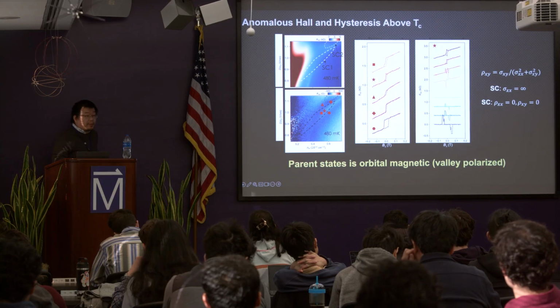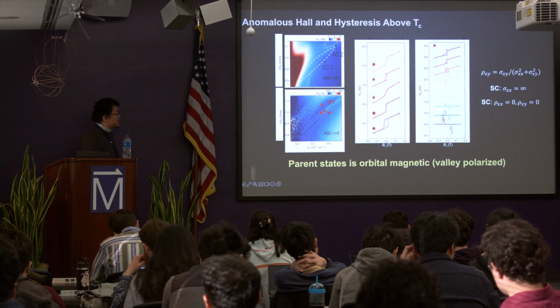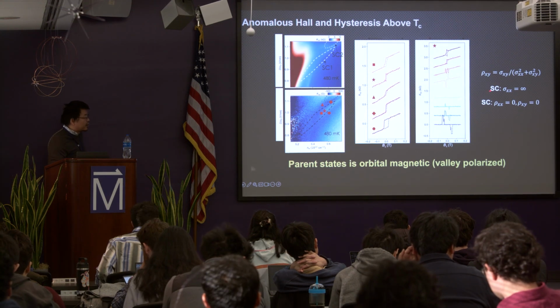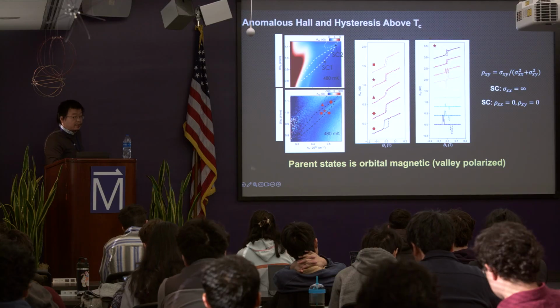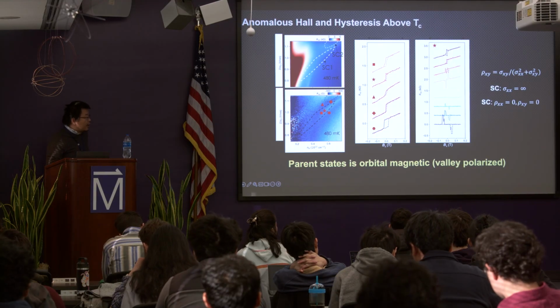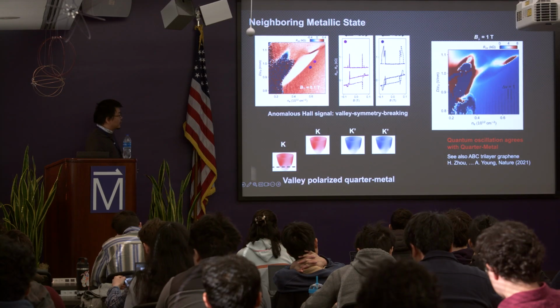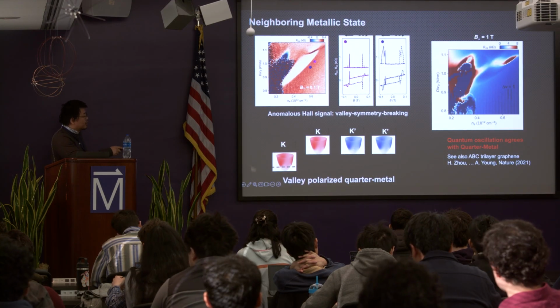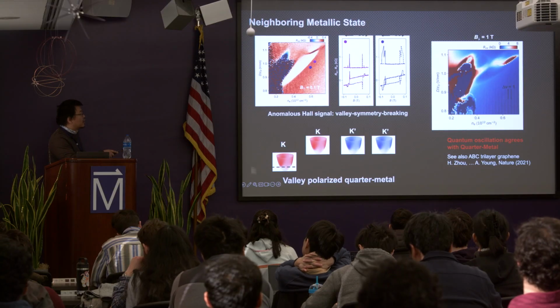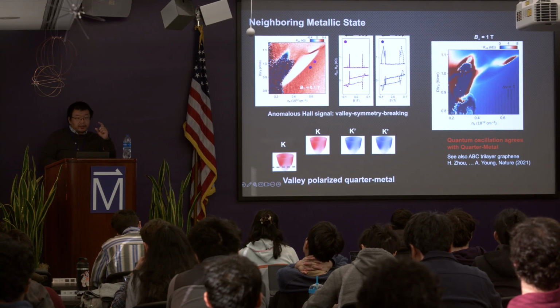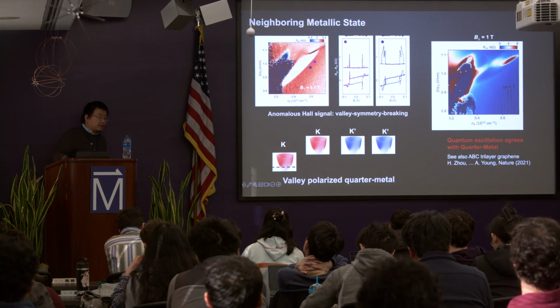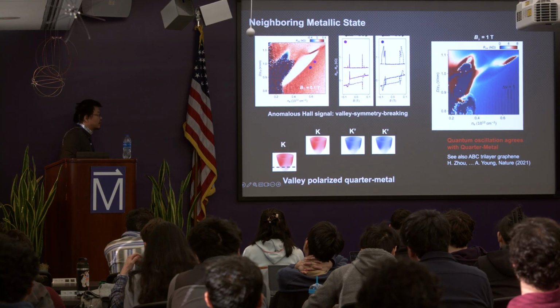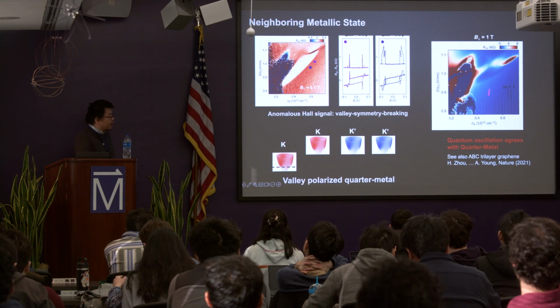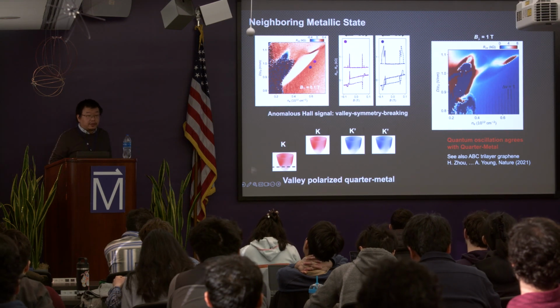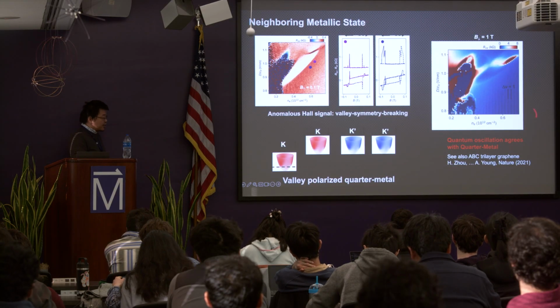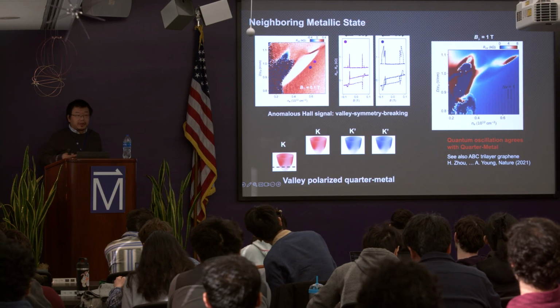So one piece of evidence is, if you warm it up and lose the superconductivity, and you check the normal state here, you do see the anomalous Hall effect in this normal state. So you have the orbital magnetization. And you can also check the surrounding states, which have a pretty large anomalous Hall effect. So basically, your superconductivity domain is embedded in a phase with a pretty large anomalous Hall effect. And if you check the quantum oscillation, you can know the degeneracy. It gives you the degeneracy of a quarter metal, which means it's a spin and valley polarized pocket.